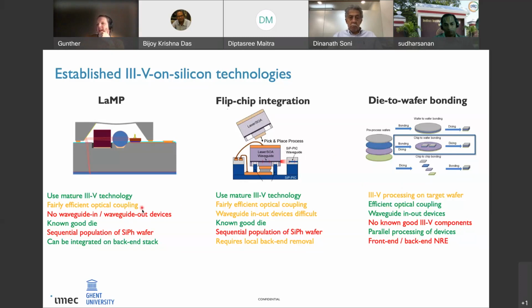On the other hand, there are also drawbacks to these techniques. For the hybrid approaches, there is the fact that it is a sequential integration process. You have to either actively or passively align the III-V component to the silicon and then put it in place. So this means this is a low throughput integration process. That's an advantage of the die-to-wafer bonding approach, because here you have the parallel processing of the devices, so the throughput is higher. Now, we believe that microtransfer printing is a technology that combines advantages of these hybrid integration approaches with the advantages of the die-to-wafer bonding approach.